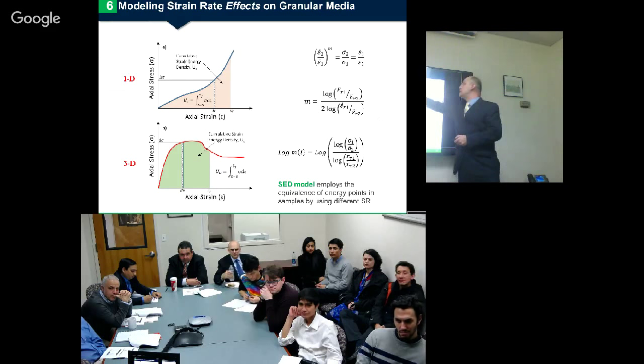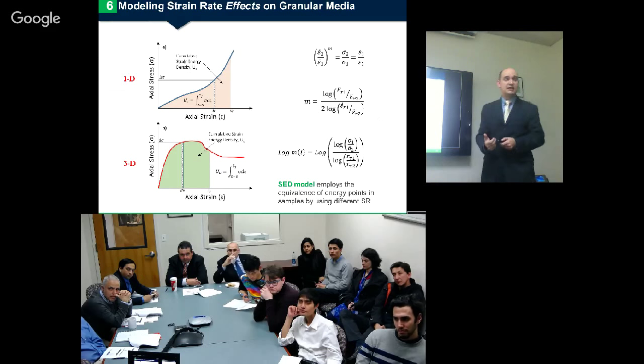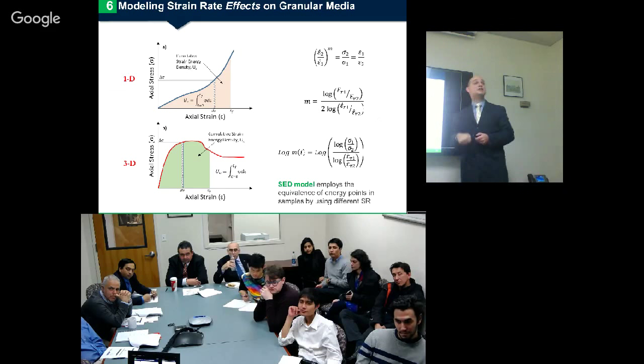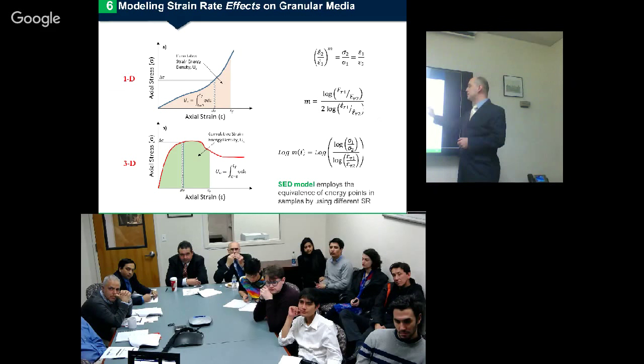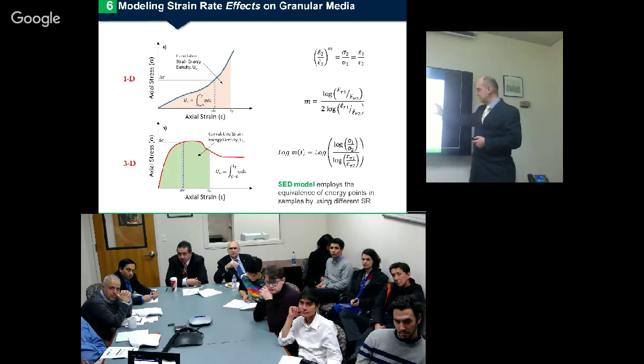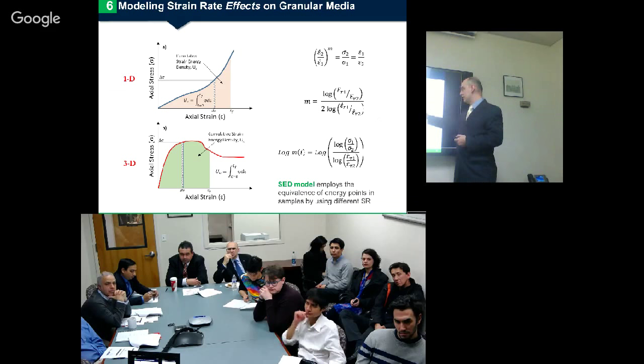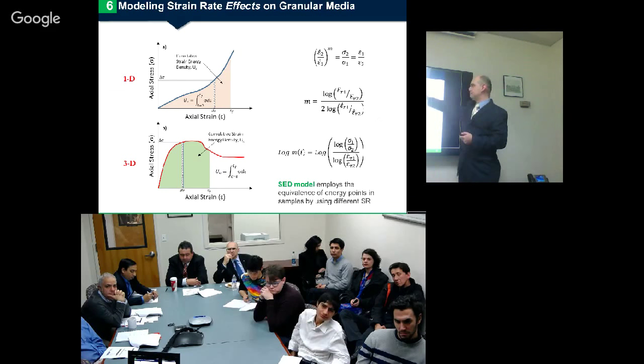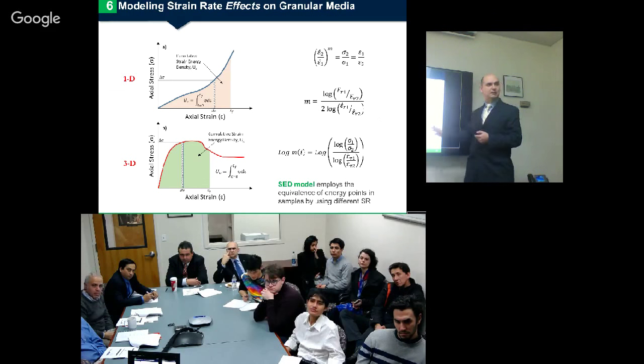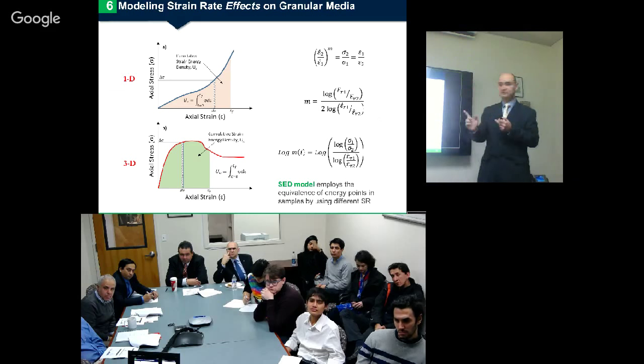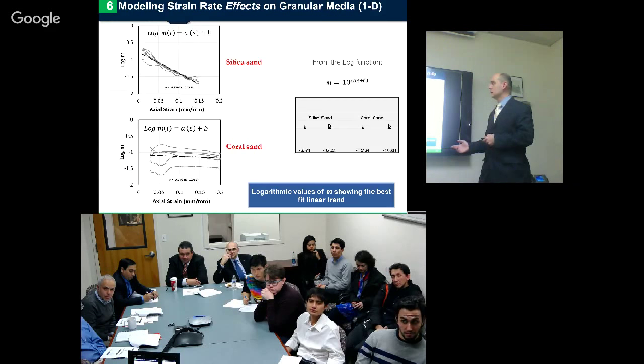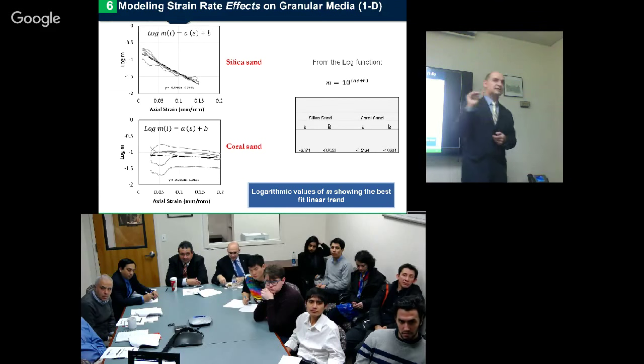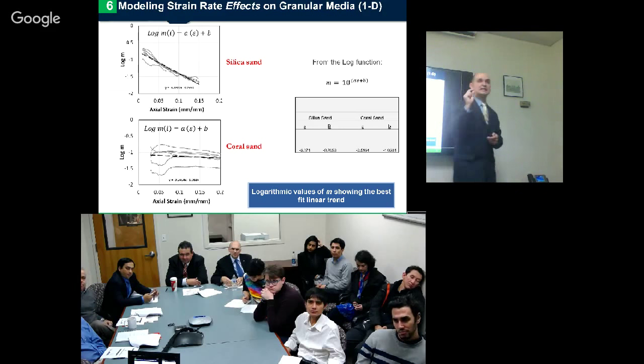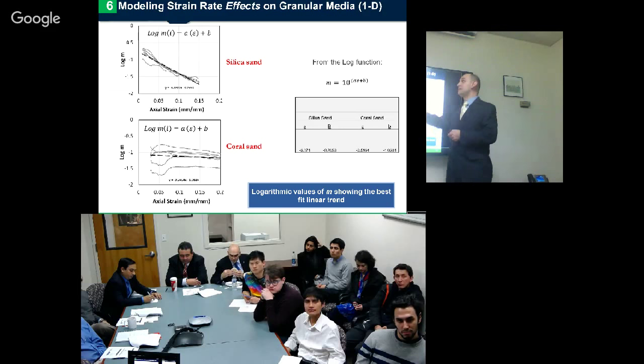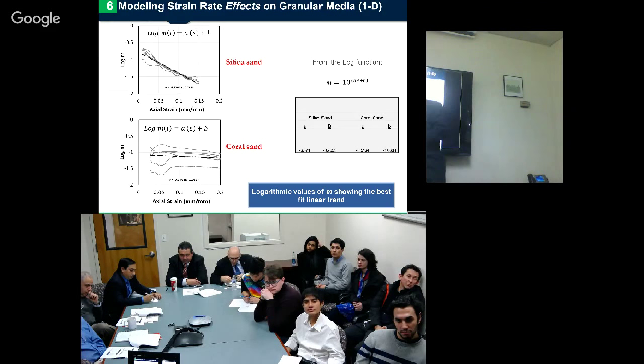So again, having this relation between strain rates, axial strain, and axial stresses, we took this from the literature, that this m value can be found by developing this analytical part. Although it might look silly, having log on both sides, the main idea of this is to go through this in order to linearize these functions. The log of m, again, m is this exponent, and m is going to vary depending on the axial deformation.